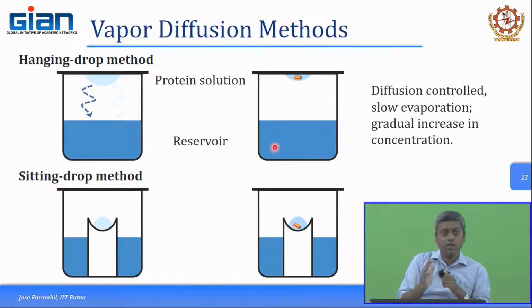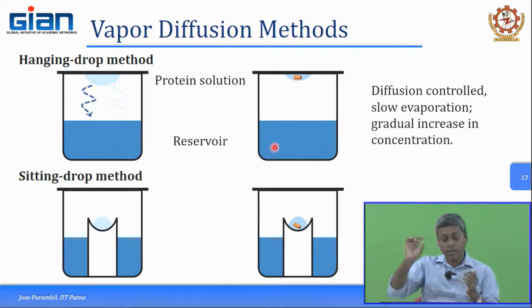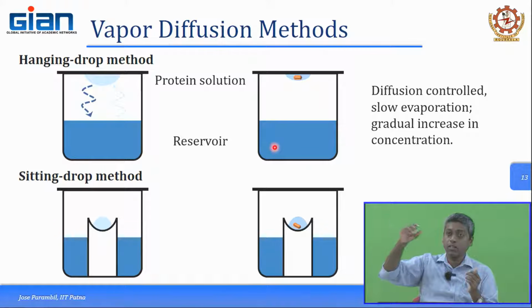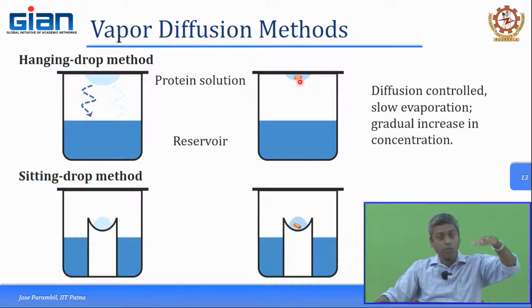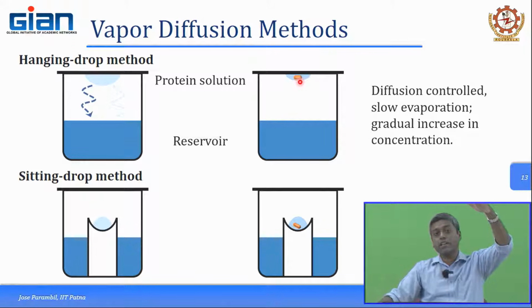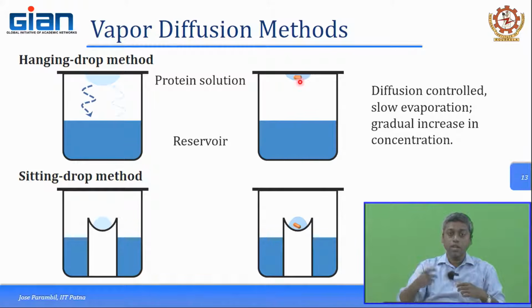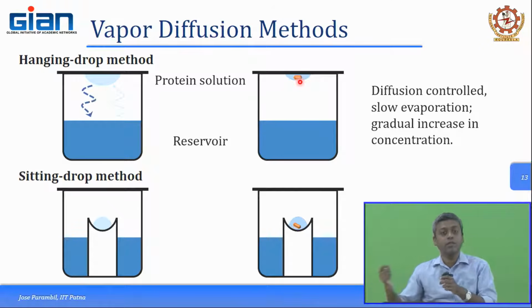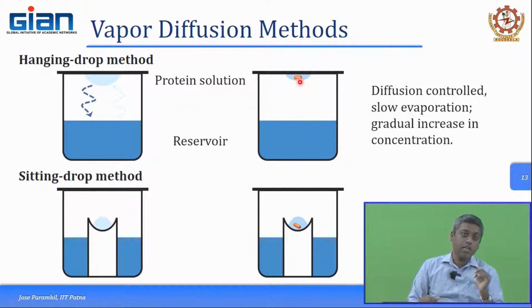Both have got their own drawbacks, because in the sitting drop method, the protein crystal which is formed might settle down at the bottom, and it might attach a little bit strongly to the bottom surface. Whereas in the hanging drop, the good thing is the crystal, because of its mass or gravity, moves down and settles at the very bottom of your droplet. So, it will not be very strongly attached to the surface. The moment you want to take it out, you can take out the cover slip and easily remove the crystal, which would be very well formed and without any deformation.